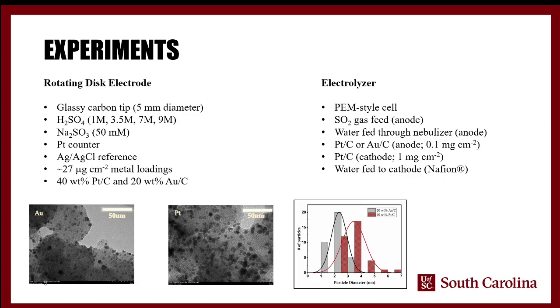We used a platinum counter electrode and a silver chloride reference. And we used a consistent loading of 27 micrograms of the catalyst per square centimeter. The 2 catalysts we had were commercial. The platinum was 40 weight percent and the gold was 20 weight percent. But again, we normalized the loadings of the metal itself, so that was the same throughout.